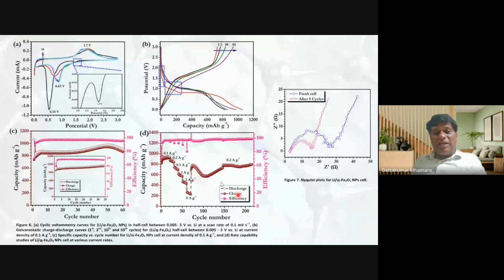This is for 200 cycles. The capacity is very high. The Coulombic efficiency of charge discharge is almost 100%. We got around 900 capacity, which is stable up to 60 cycles. So this kind of results we got.